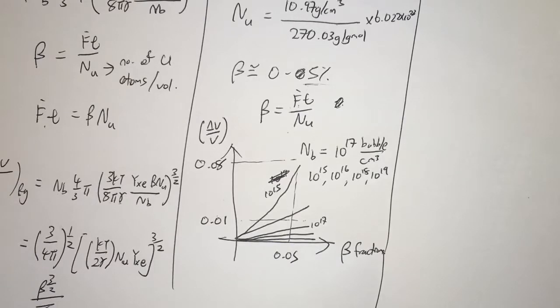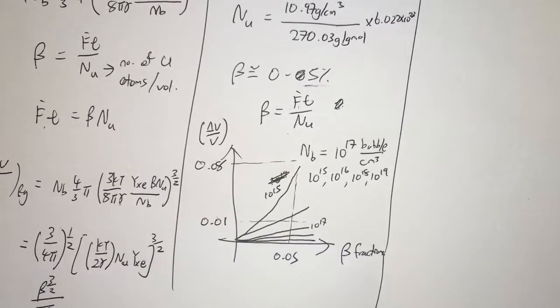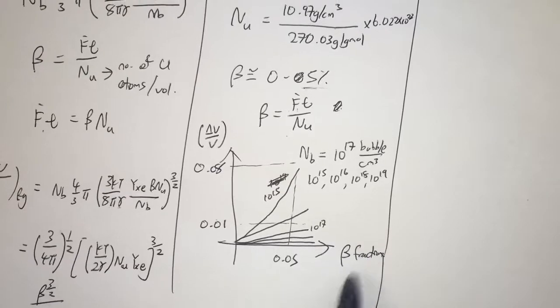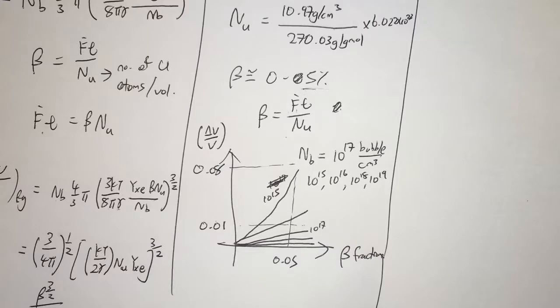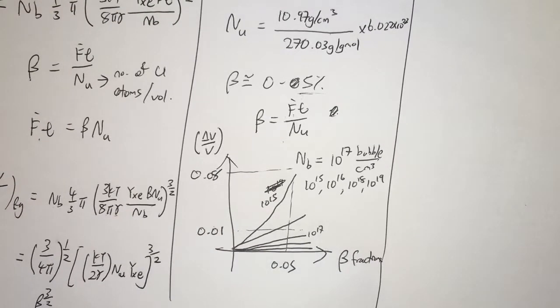Okay. So we may not get the bubble number density from, let's say, a pure mathematical derivation. We can still look at micrographs of fuel and get a guesstimate of bubble number density post-extraction from the reactor. And then we can refer back to these graphs to try and predict how it expands over time. And this is very useful for us to understand how much the fuel swells as a function of burn-up or time equivalently, depending on the characteristic bubble number density.